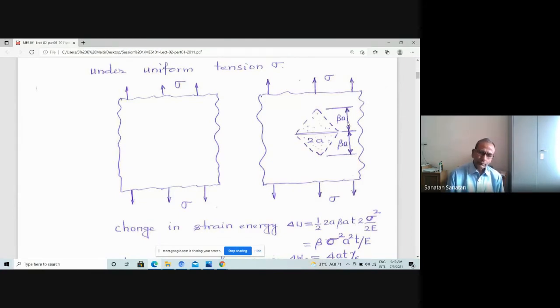And therefore when a crack is extending, it should be able to supply the surface energy required per unit area of new surface to be created, and obviously that energy comes from the strain energy of the material. You have strained the material, you have given strain energy as input, and as the crack extends, that strain energy is actually getting converted into surface energy.